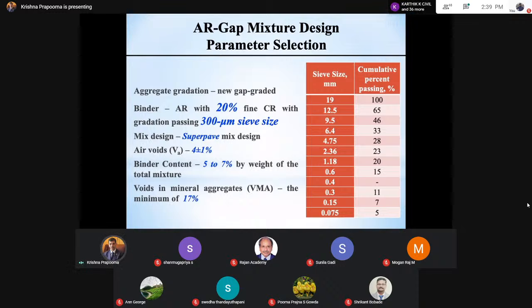So here there is no raveling at all because you are having a very high value. See here, 17%. Now the effective binder volume is about 12 to 13%. Air void is about 4%, so that makes it 17%. If you look at the dense graded, the effective binder volume will be around 8%. The air voids will be around 3 to 4%. That makes it 12%. So here it is about 5% more. So that makes it a rich mixture, having a very high amount of binder content. Very good, it'll arrest raveling, cracking, rutting, and so forth.